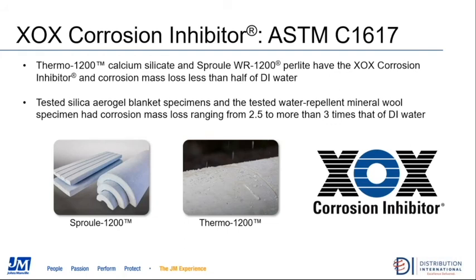So to somewhat summarize what we just reviewed relative to the ASTM C1617 testing that's been done, you can see that insulation materials that do have some type of an active corrosion inhibitor in them do show a substantially reduced corrosion rate than either DI water or insulation materials that may not have a corrosion inhibitor but still offer some type of water repellent or hydrophobic properties.